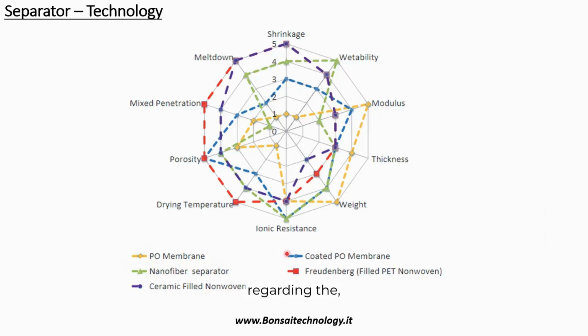Currently, there are some studies regarding the non-woven and the nanofiber separator. As you can see, non-woven and nanofiber separators have very great properties in terms of meltdown, shrinkage, wettability, good property in terms of ionic resistance, and even for the other KPIs. The problem is that it seems not possible to achieve very thin thickness and very light separator for non-woven and nanofiber. This is the reason why the score is lower compared to the PO membrane, but